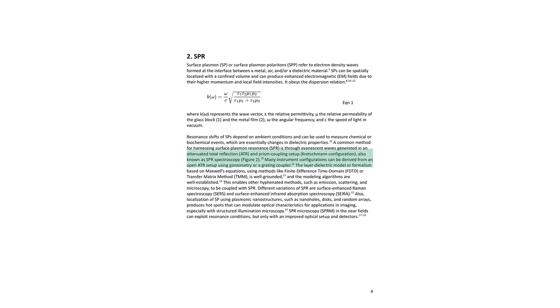A common way to harness this phenomenon is with an experimental setup known as the Kretschmann configuration. In this setup, light is shone through a prism onto a thin metal film, typically gold, deposited on a glass slide. At a specific angle of incidence, under conditions of total internal reflection, the light energy couples with the electrons in the metal film and excites a surface plasmon. This coupling causes a sharp drop in the intensity of the reflected light. The angle at which this minimum occurs is the SPR angle.